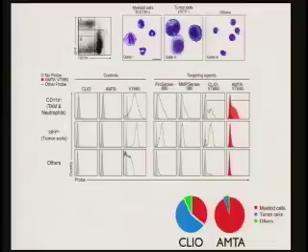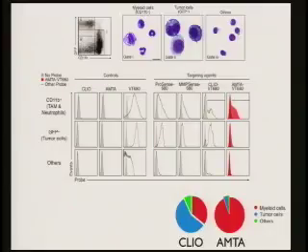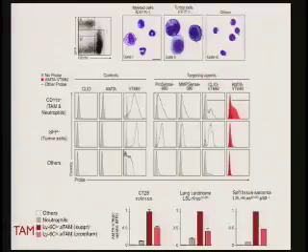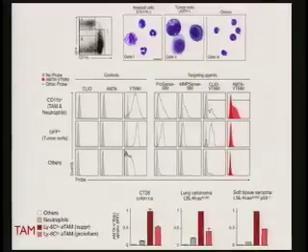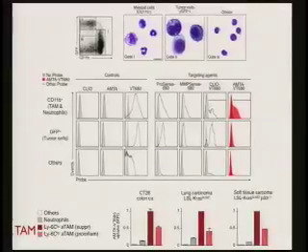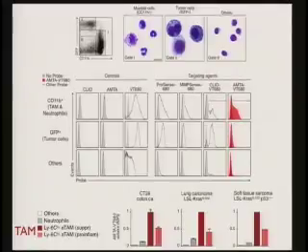Only half of it targets macrophages. So this goes against the paradigm that nanoparticles just end up in macrophages. However, the small molecule derivatized agent is over 95% specific now for activated macrophages. And in other models, such as a CT26 colon cancer, Tyler Jacks's KRAS lung cancer model, or soft tissue sarcoma model, this compound here, AMTA, is highly specific for tumor-associated macrophages.